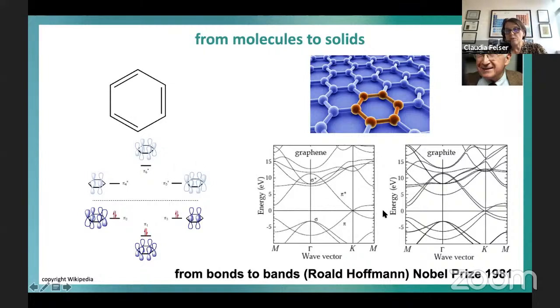Here we have the same situation, more or less, the occupied bands and the unoccupied band for a layer of graphene. At the gamma point, they are identical to the MO diagram, but since we have translation symmetry, our bands get an additional phase, and so we have this very nice band structure.